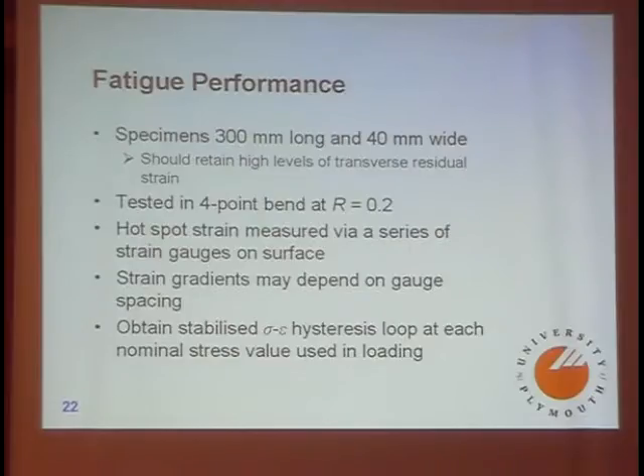Now the thought that crossed my mind this morning is it would have been nice to have measured the residual strain on stabilized specimens, although when we've done work on what fatigue loading does to specimens, there is no plateau in the residual stress. It actually just keeps steadily decreasing as far as we can tell, as long as you're prepared to fatigue cycle them. But you still end up with high levels of residual stress. I would not have been able to test those plates. They're actually very deformed as welded, so you have a problem that you're going to load them unevenly, and therefore you're going to end up with residual stresses in the plate that represent the fatigue loading you've done and not the original weld, I suspect. So I figured it was better to deal with the as-welded residual stresses rather than try and load a deformed plate that would do strange things to the stress field.